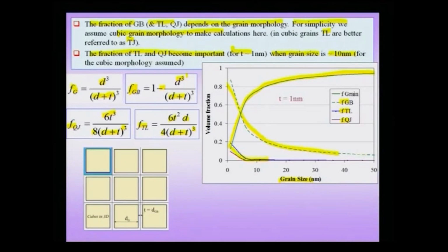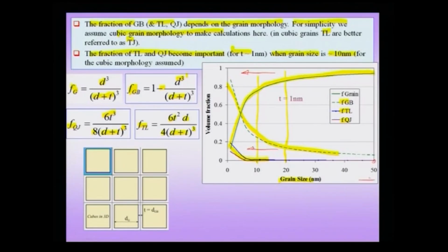The important point to note from this graph is that it is only below about 10 or 20 nanometers. So, I can draw some vertical lines around this 10 nanometer or 20 nanometer. In this regime, which is below this size, grain size effects start to dominate on these other entities of the crystal. That means, if I am at a larger grain size than about 50 nanometers, then I can safely ignore the contribution of these to density, because the volume fraction is going to be small, and therefore I can ignore them.